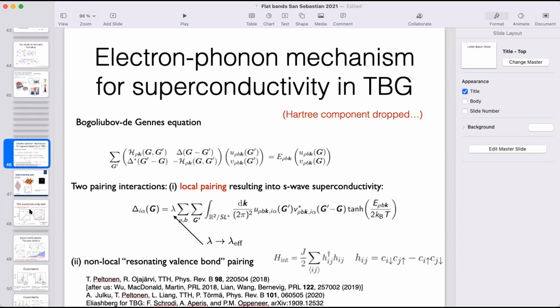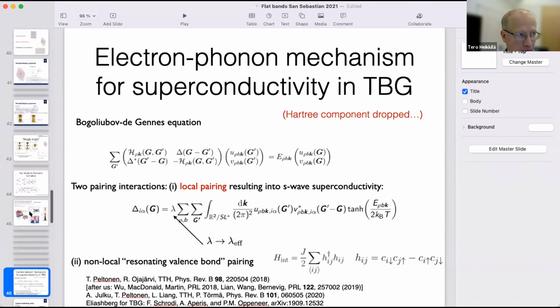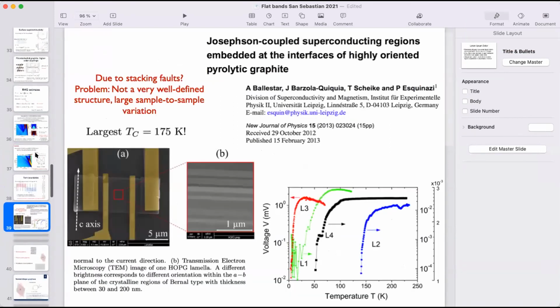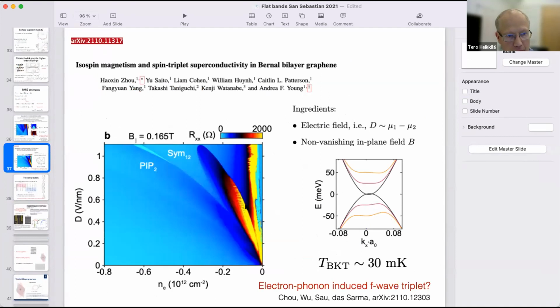I think before closing, I would like to ask a question, because I think you mentioned at some point that the delta could have some momentum dependence, but of course the order parameter can also have some non-trivial spin dependence, and this is connected to some experiments with in-plane magnetic fields and so on. So whether it's P-wave or for example, and so on. So am I correct that you're assuming that the order parameter is s-wave all the time in this spin?